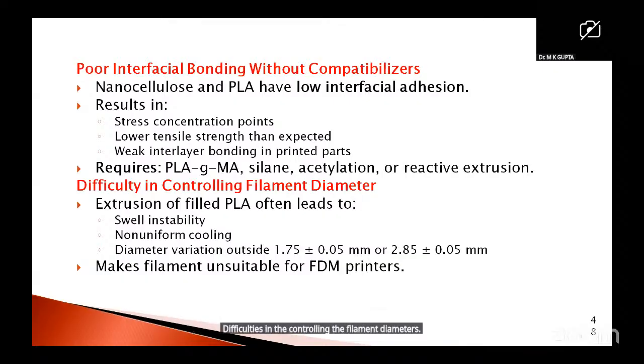Difficulties in controlling the filament diameters. Extrusion of the filled PLA often leads to swell, instability, non-uniform cooling, and diameter variation outside. Mixed filaments are unsuitable for FDM printers.